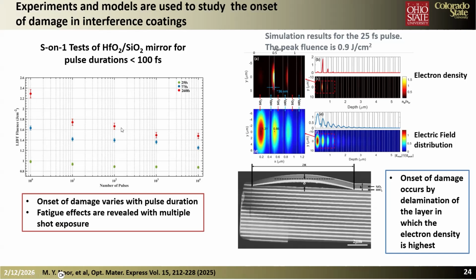The way to think about it is, now I have a high repetition rate in this case. So the damage threshold is dependent on pulse duration and on repetition rate. What we also showed with our colleagues at Northeastern is that the onset of damage occurs via delamination in the layer where the critical electron density is the largest. And that's what these plots here show.